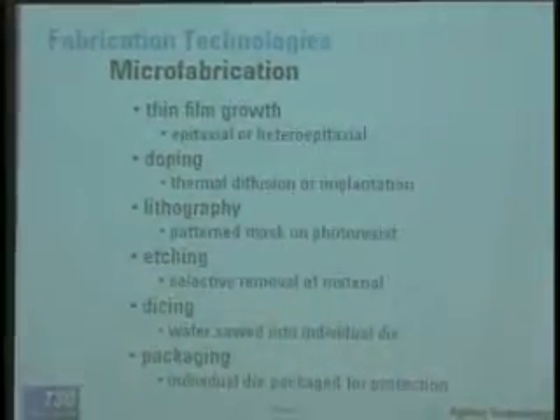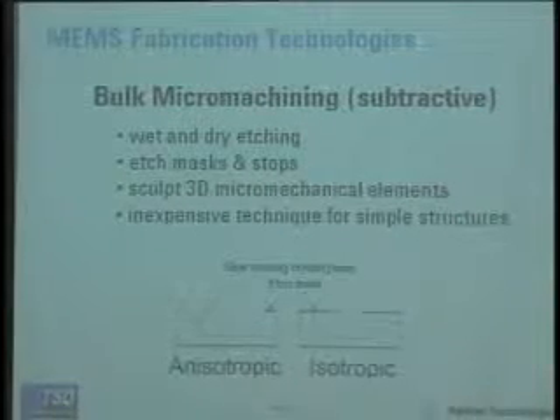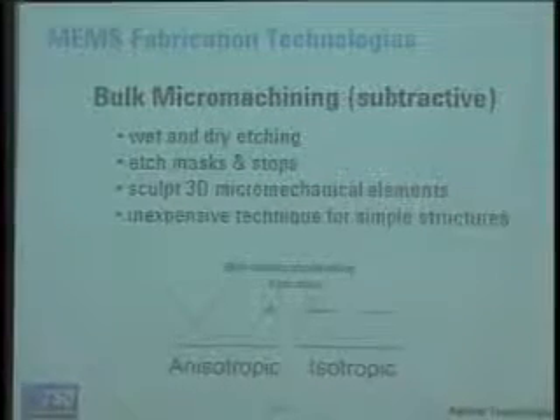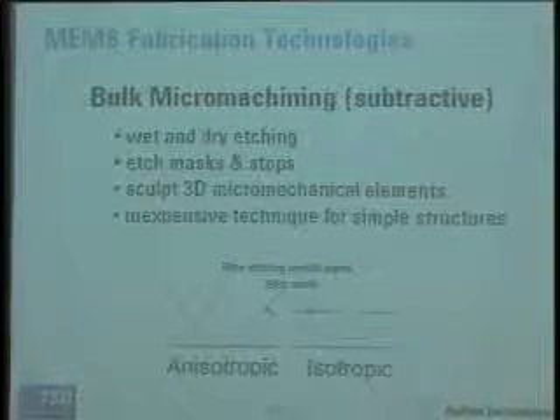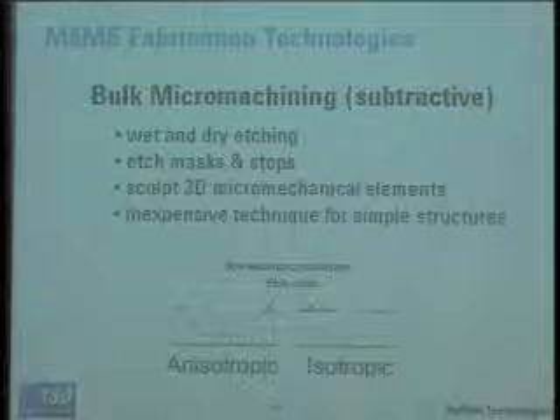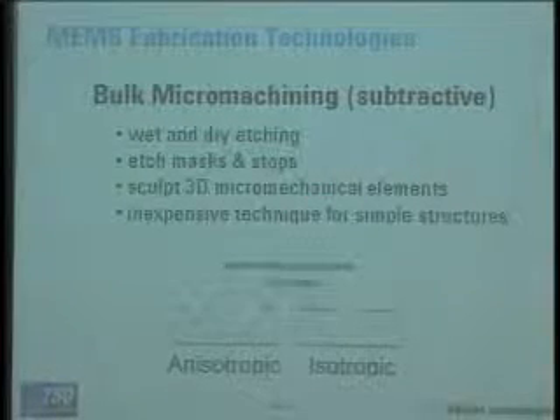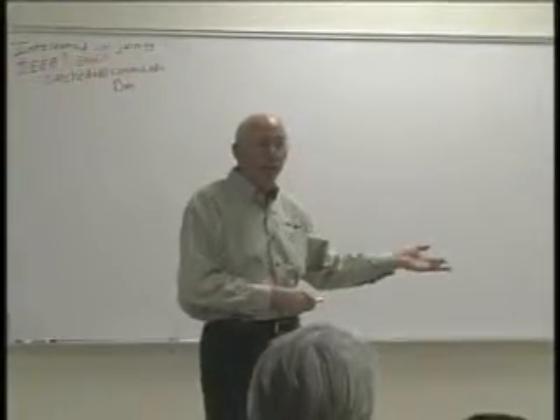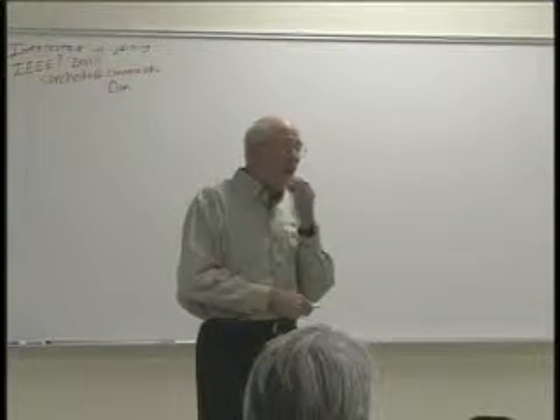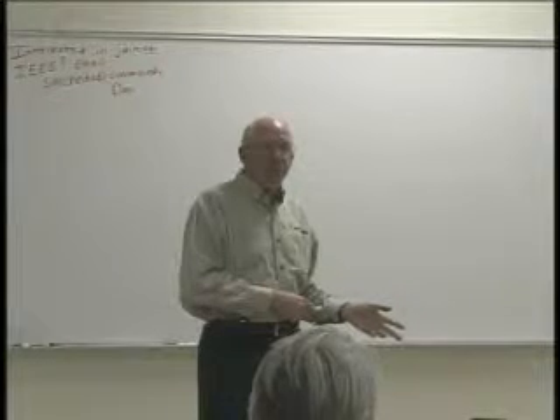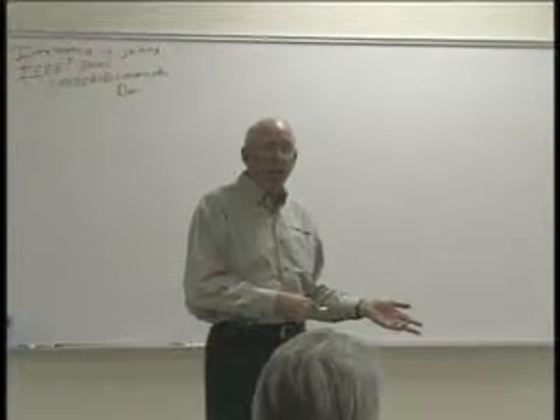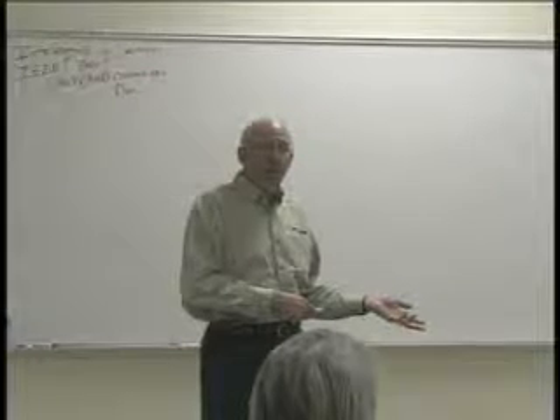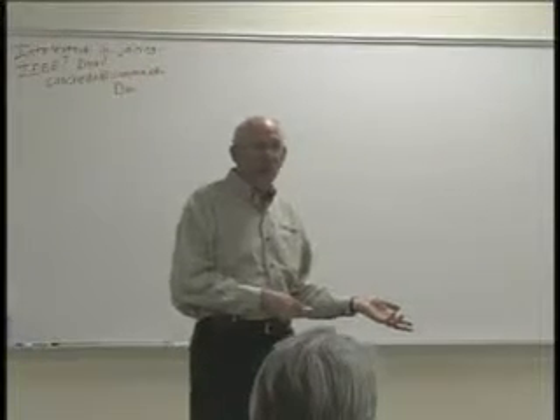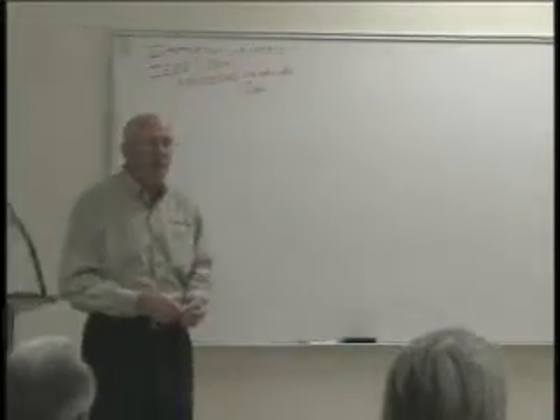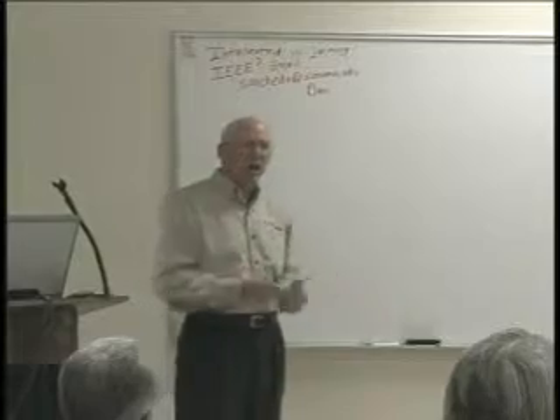Sir? What is the packaging temperature? What temperature do you usually prefer for the MEMS fabrication? Probably the highest temperature that anything sees is going to be in the packaging if you're doing a wafer level packaging process. Generally, those processes are up around 275 to 350. For MEMS, you can get away with that. You can get away with 350. But in semiconductor processing, many of the devices will not withstand temperatures over, say, 250, 275, so you have to be careful with that. But that would probably be the highest temperature that one sees.